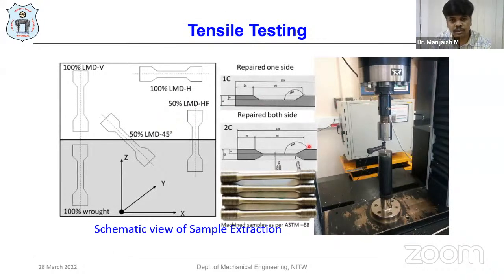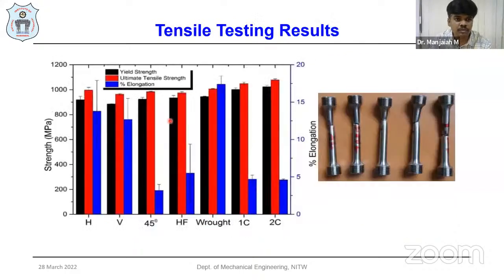And we have tested the different mechanical properties, either tensile, fatigue, or crack propagation testing, in different orientations, for only-manufactured components and repaired components, as well as different inclination angles, which is one-side repaired or two-side repaired. And if you see the tensile results, the strength is very, very good.